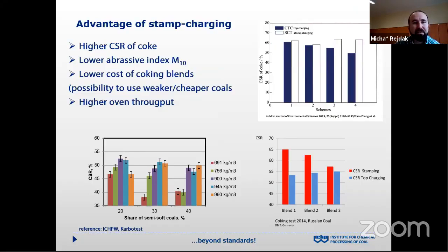What is the advantage of stamp charging? As I said before, the higher bulk density of coal charge enables the production of coke with higher coke strength after reaction index, lower abrasive index. I mentioned lower cost of coking blends, and of course, higher density is related to higher oven throughput. But about the coking quality parameters, I will say in the next slides.